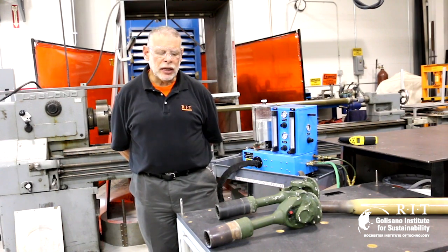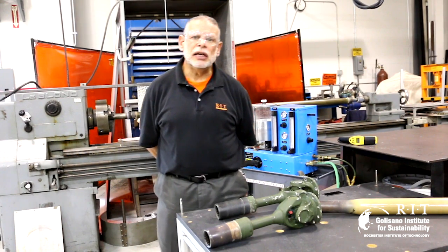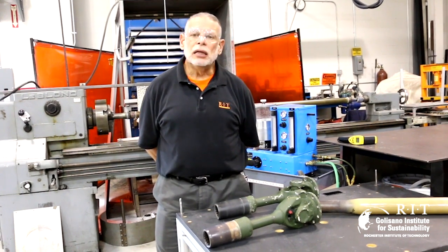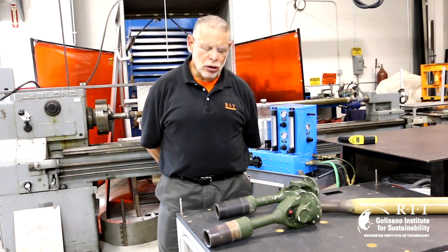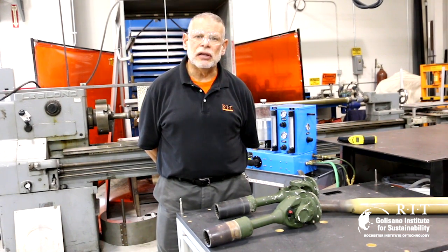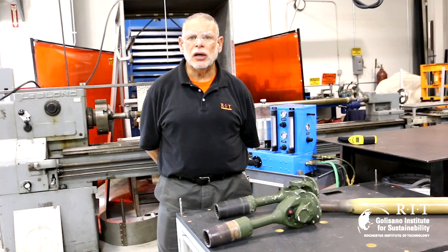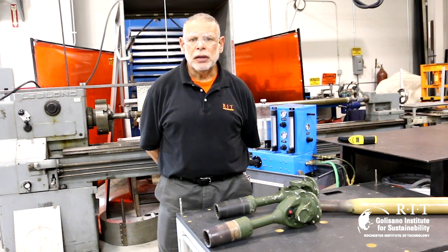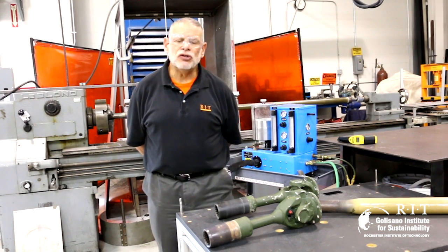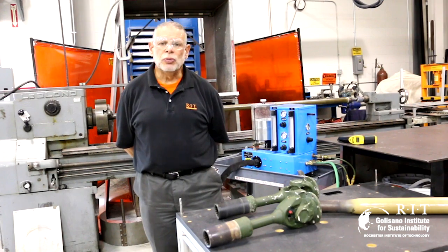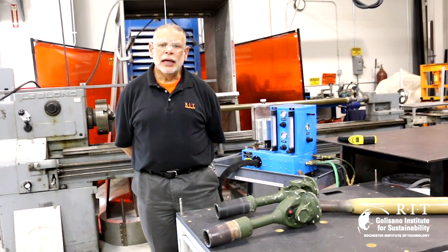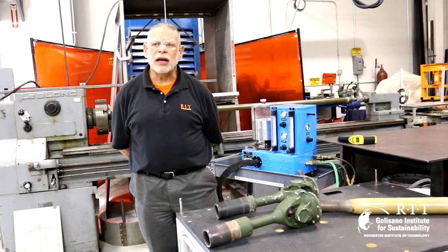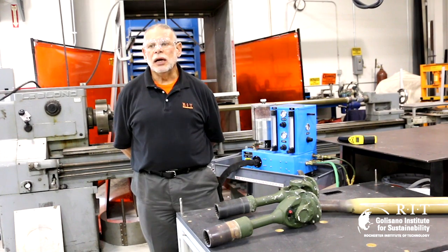But one of the things we found out when we did the failure analysis, we understood why the coating was coming off or debonding and getting water underneath it, because of the split between the coating and the step. So when we designed the remanufacturing process, what we did was we brought the coating over the step, and so it solved the problem. So actually, the part is better than the new one.